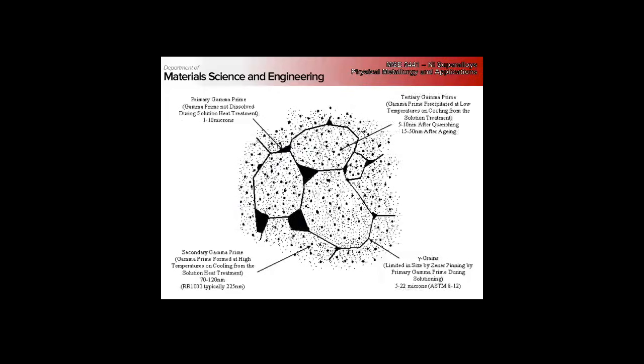Yeah, so generally we don't want primary gamma prime. It forms on very long, slow cooling and aging, giving us gamma prime grains and gamma grains. In solution heat treatment, we typically want to dissolve all the primary gamma prime, but in some situations we don't actually - so we have remnants of the former large gamma prime grains that haven't completely dissolved. So I was wondering, does it have a bad effect just because of the grain boundary? It seems it can act as particles at the grain boundaries.